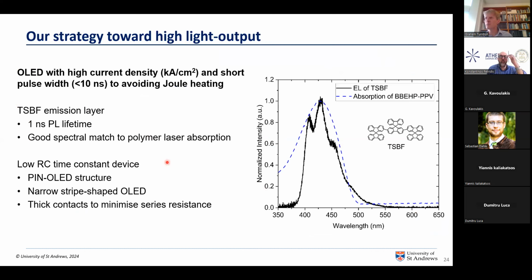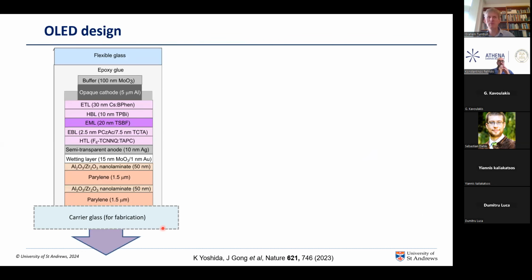The idea here is that we take a blue OLED based on this molecule, TSBF, which has a short lifetime and a good spectral match to our best organic semiconductor gain material. We engineer the device to have a PIN OLED structure that lets us reduce the series resistance of the device. We engineer its shape to minimize RC time constants and maximize injection of light into the gain medium, and we engineer the thickest contacts anybody's ever thought to make on an OLED to fight against series resistance.